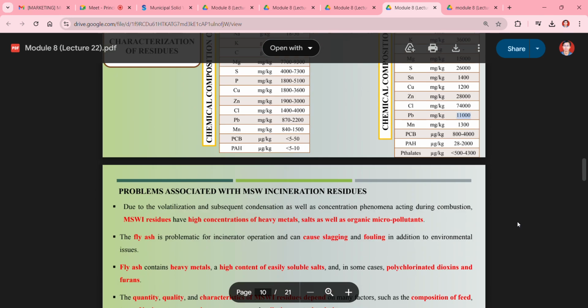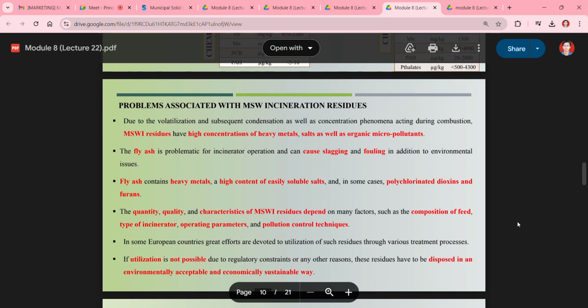the municipal solid waste. So there are some problems associated with the MSW incineration residues due to the volatilization and subsequent condensation as well as concentration phenomena acting during combustion. MSWI residues have high concentration of heavy metals, salts as well as organic micropollutants. The fly ash is problematic for incinerator operation and can cause slagging and fouling in addition to environmental issues. The fly ash contains mainly heavy metals, a high content of easily soluble salts, and in some cases polychlorinated dioxin